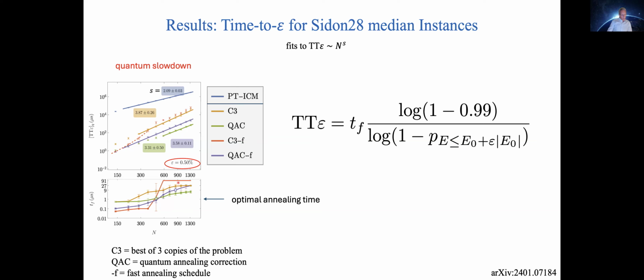So, okay, we have optimal anneal times. Except that for QAC, you see the curve doesn't continue because the optimal anneal times actually stop for small problem sizes. We're not able to establish an optimal anneal time for the smaller problem sizes. So when the interpolation or the fit stops, that means that we were not able to optimize the anneal time. All right, so with that in mind, unfortunately for epsilon 0.5, which is a very small optimality gap, the slope, which is given by these numbers here, for PT-ICM is the smallest. It's smaller than for the quantum methods.